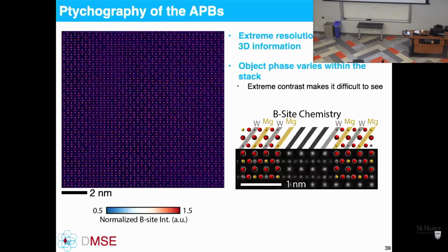So what I'm going to show here is a little video of our multi-slice reconstruction, and each frame of the video is a different slice along the thickness, right? And what I'd like you to note is that as I play that video, you probably can't see anything, right? It's very difficult. That's because the contrast of ptychography is so high in comparison to what you're normally looking at in one of these HAADF images that it gets hidden.